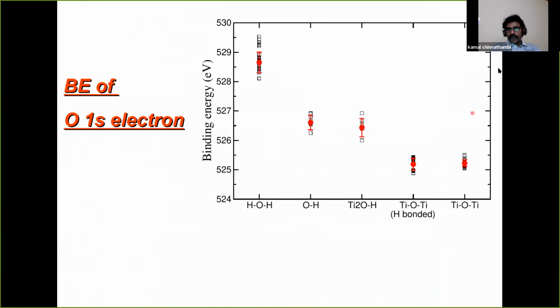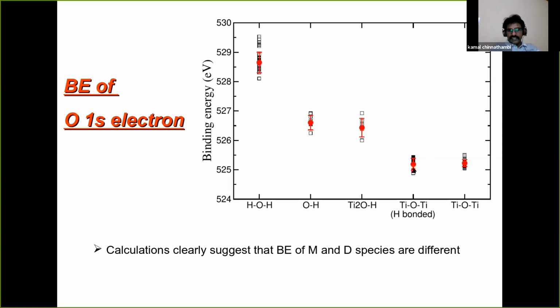Before going into the details, what I have done is first segregate all the classes, the species, and then look at the energetics. The first most important thing is that we can see a bunching of all the water molecule signals, and they are very much separated from the dissociated species. So there is a good difference between them. Another thing is that there is also a difference between the dissociated water molecules and the oxygen from the titanium oxide. This is exactly the trend we see from the first slide of the experiments. So that is good. We clearly see that even from the theory we could distinguish between these two species, and the order is maintained as in the experiment.